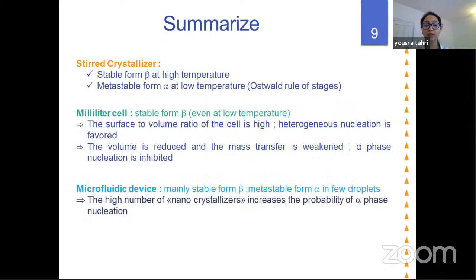In the microfluidic device, we mainly observe the stable phase beta with the metastable phase alpha in few droplets. When we compare this result to the milliliter cell, it is more or less the same, but there is one difference: in the microfluidic device, the high number of nanocrystallizers increases the probability to observe the alpha phase nucleation.